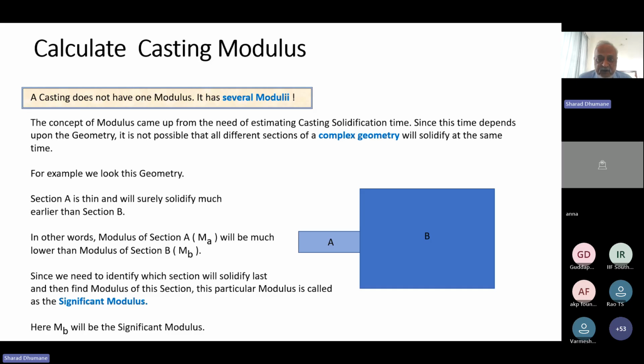When casting is solidifying, we want a feeder on the top of the casting, which solidifies after the casting solidifies, so that it is in liquid state and supplies liquid metal to the area of casting which is solidifying and shrinking, and compensates that shrinkage. To do that work, it must have a higher modulus. In other words, it must solidify later than the casting.